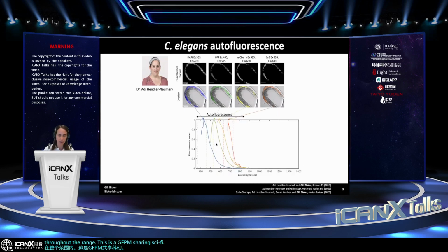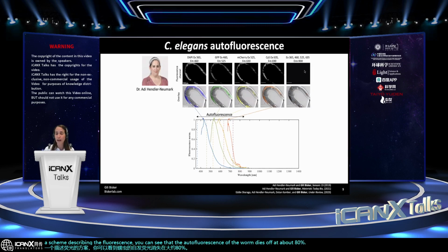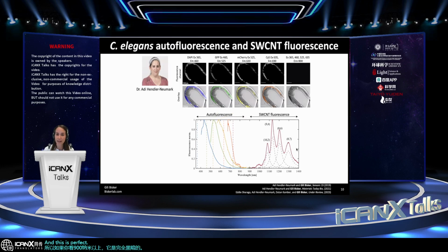Okay, so you can see a scheme describing the fluorescence. You can see that the autofluorescence of the worm dies off at about 800 nanometers. So if you look above 900 nanometers, it's completely dark. There's no background. And this is perfect because this is exactly where the nanotube fluoresces. So you have a complete spectral separation between the autofluorescence of the organism and the fluorescence of our nanoparticles.